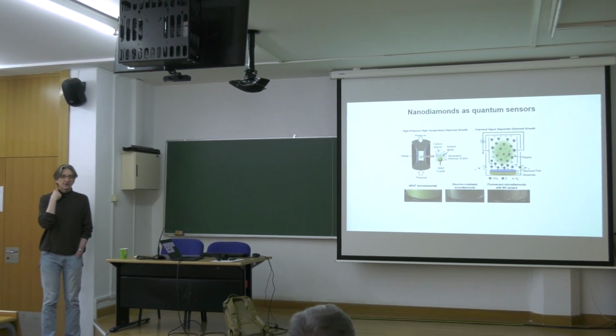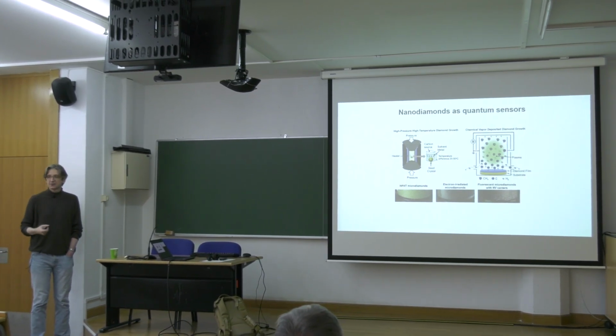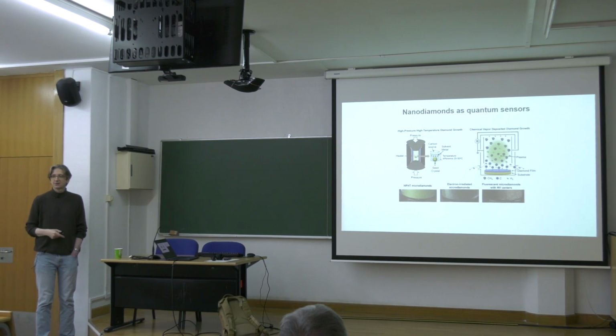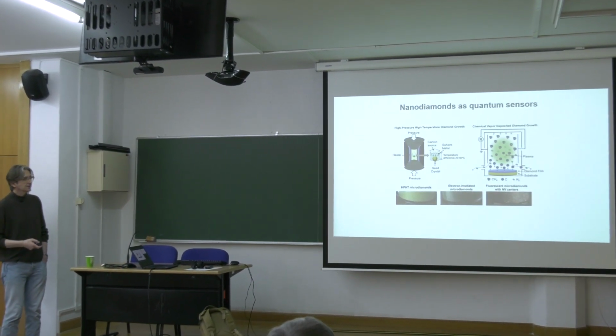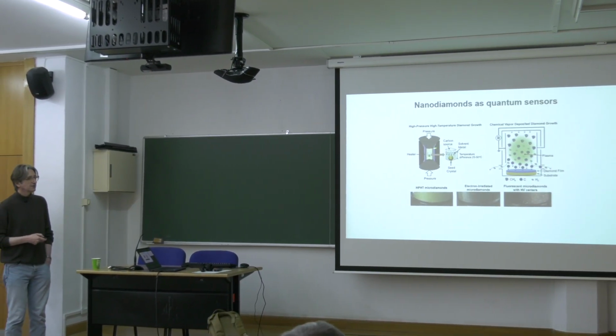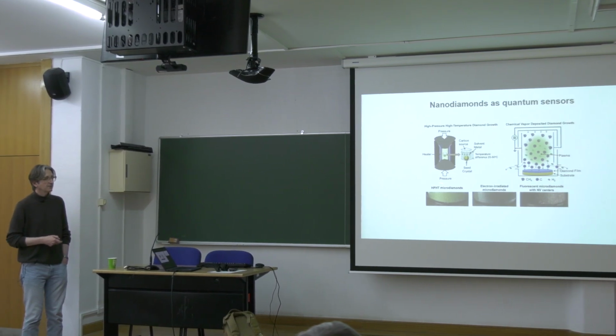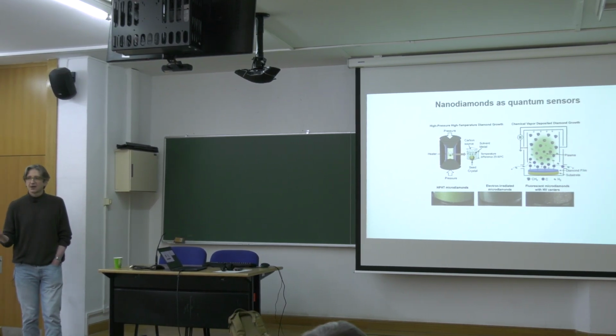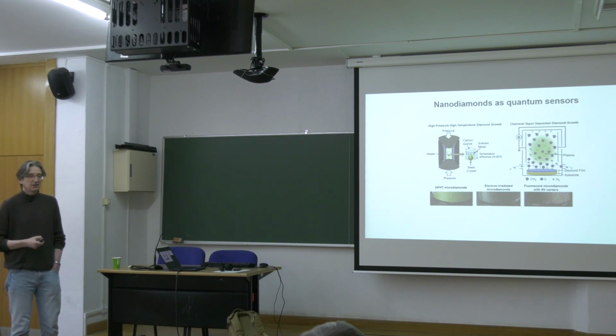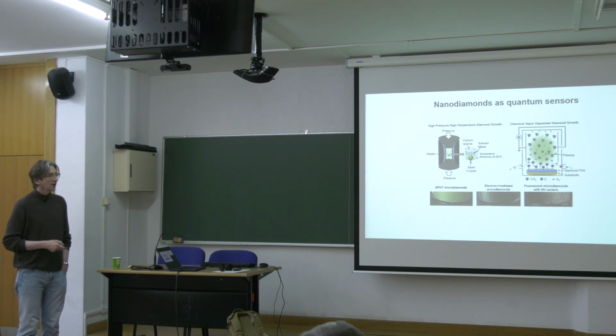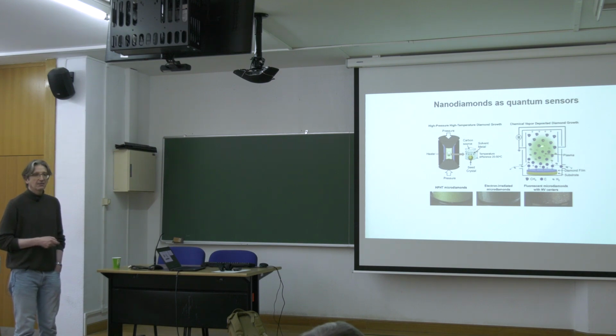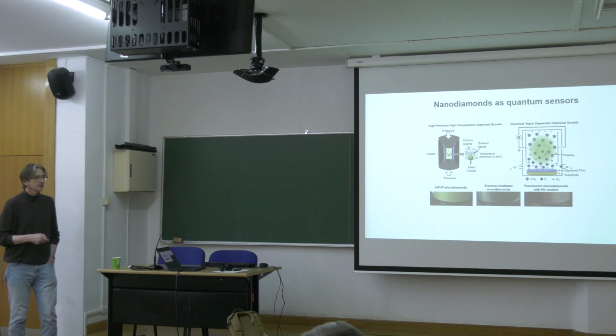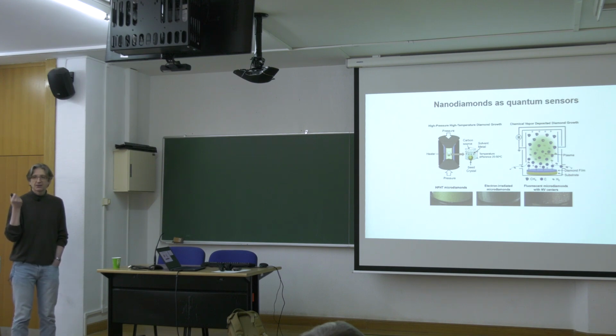So how to produce these nanodiamonds? There are actually two ways to produce diamond particles. You can produce nanoparticles by milling larger particles. It can be high pressure, high temperature synthesis of diamonds, producing diamond powder first with a size of 100 micrometers, and then it can be dispersed and milled to a nanometer size. There are also other approaches, producing diamond in plasma conditions, in chemical vapor deposition, and in some cases there is even self-nucleation of diamond particles in the plasma, and they fall down like snow, basically accumulating on the surface.